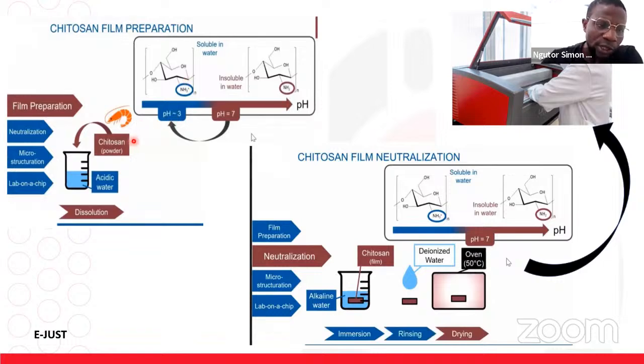So to prepare it, we had to dissolve it in an acidic medium to protonate it, to protonate the amino group of the chitosan, and then you make it soluble. After which you dry it and redisperse it in an alkaline medium. When you redisperse it in this, you are trying to deprotonate it again, and then centrifuge it and dry it at 50 degrees. So after drying it, we make a drift channel.